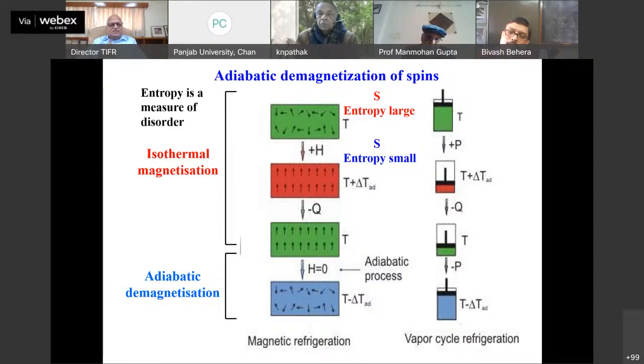Same thing you do with the spins. Now you are talking about nuclear spins. They are pointing in random directions at high temperatures; apply a magnetic field and orient them along the magnetic field direction. There is a heat of magnetization, delta T, that you cool with the dilution refrigerator to take this heat out. So then you get back to the temperature T with the field at a finite field, and then you do adiabatic demagnetization. Then you will see that the temperature cools down, and that is called magnetic refrigeration.